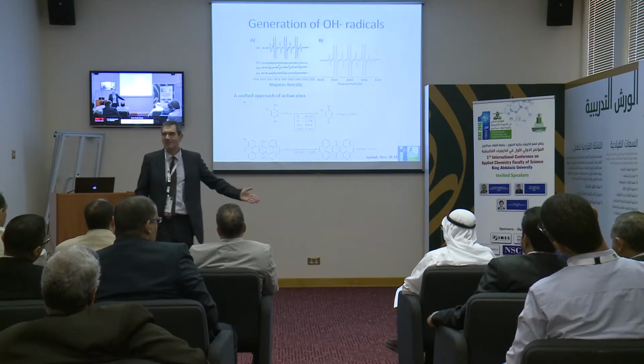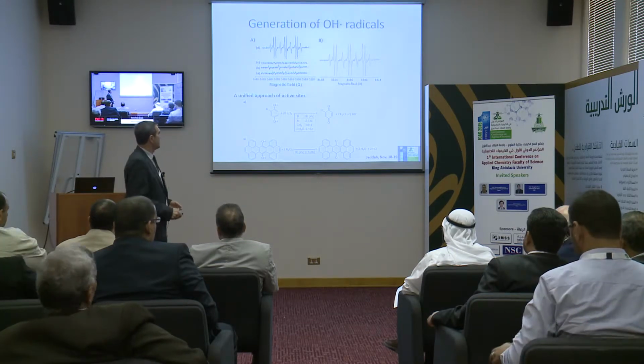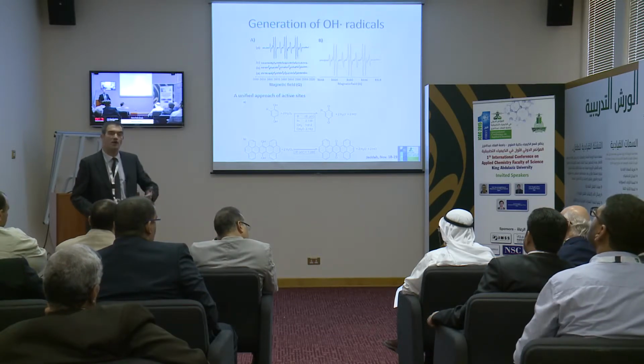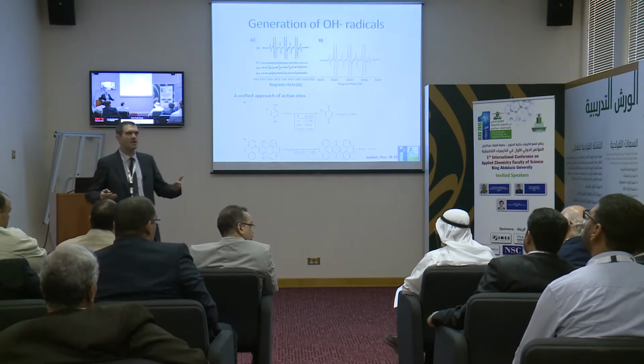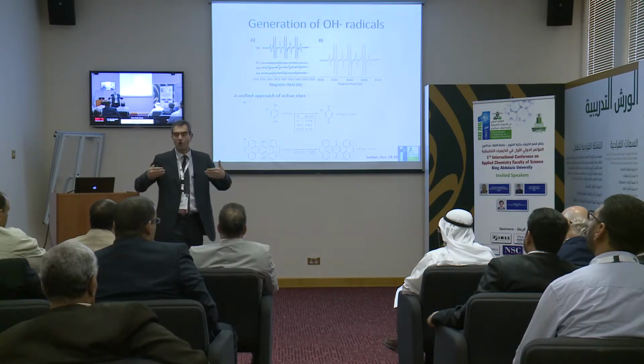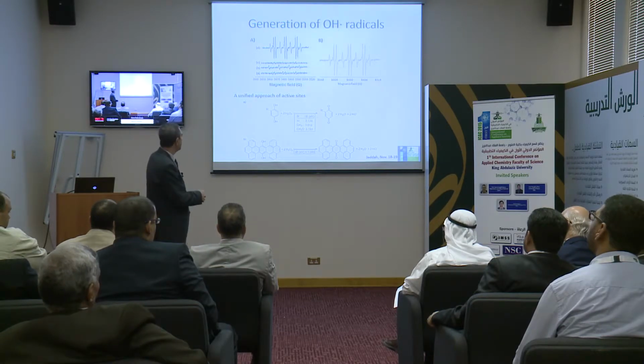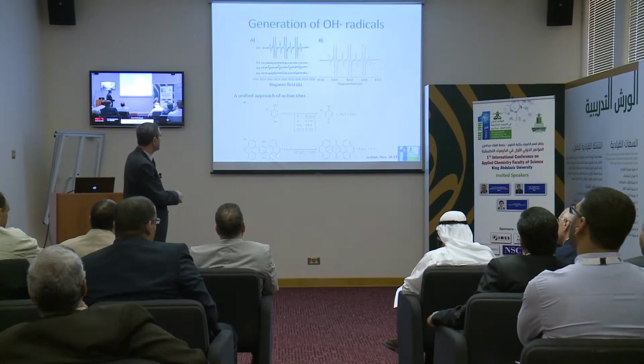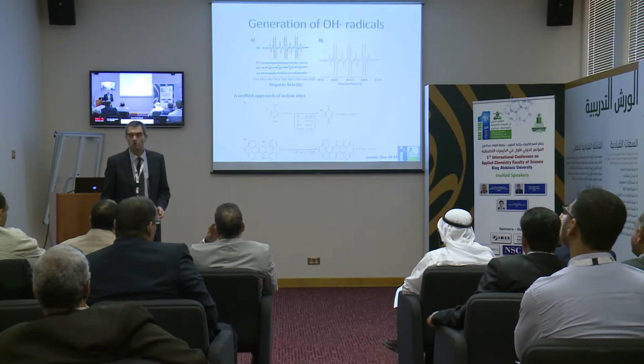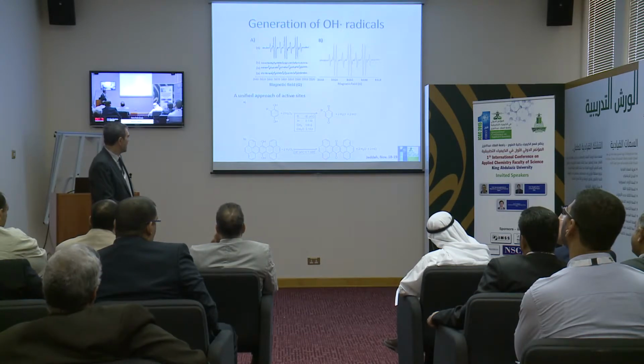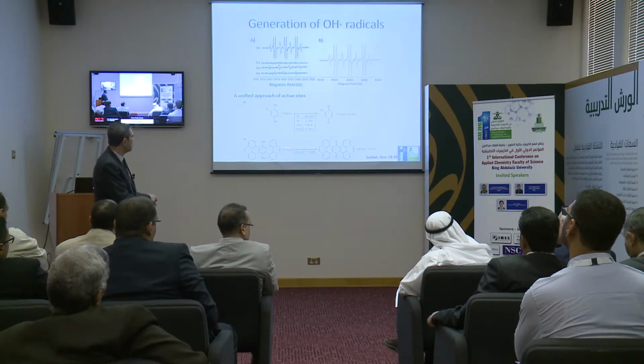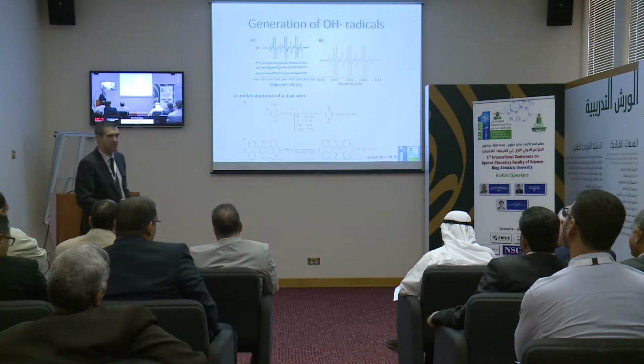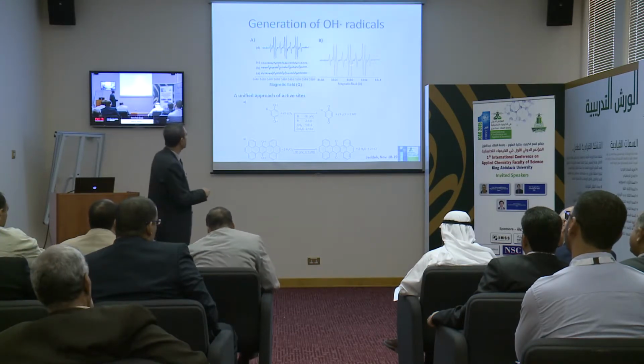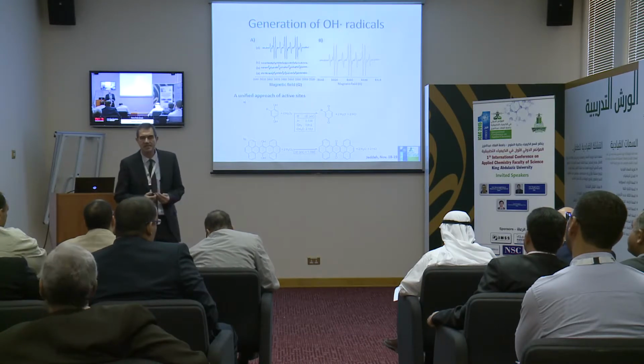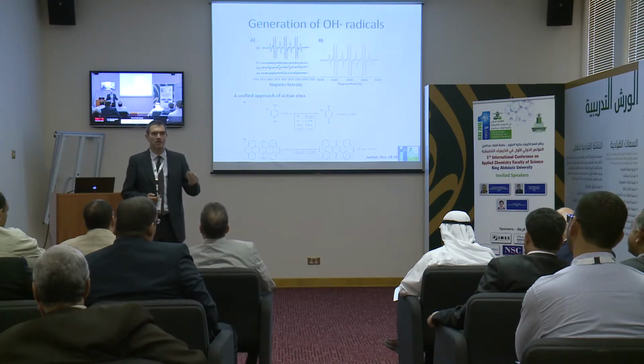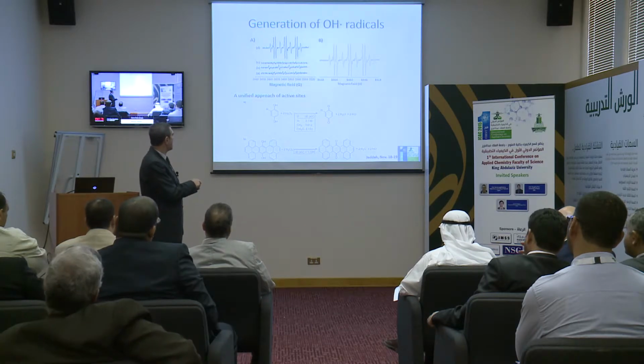One thing that I have not commented on, and probably now is the moment, is that graphene has nothing special compared with other organic molecules. So really, carbocatalysis and organocatalysis are not so different. And here we have some other molecules, for instance this one, that is also able to do Fenton chemistry in the absence of metal. So with these probe molecules, we have shown that it's also possible to generate the Fenton reaction. This leads us to the conclusion that the centers we need in graphene to promote Fenton reactions are these, quinone and hydroquinone.